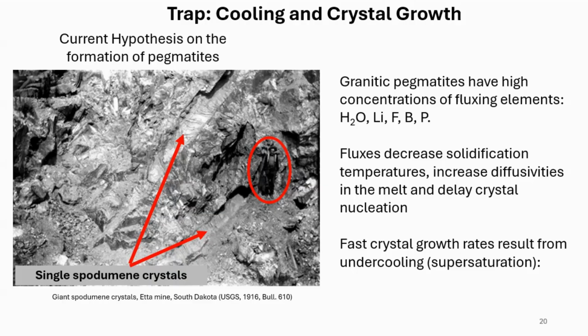Why are they large? Because the diffusivities are fast enough that you can grow large crystals. If the diffusivities are too slow, the crystal growth will just stop. But if the diffusivities are fast enough, you can grow large crystals. And you have this supercooling. So most pegmatite textures are related to supersaturation or supercooling phenomena.